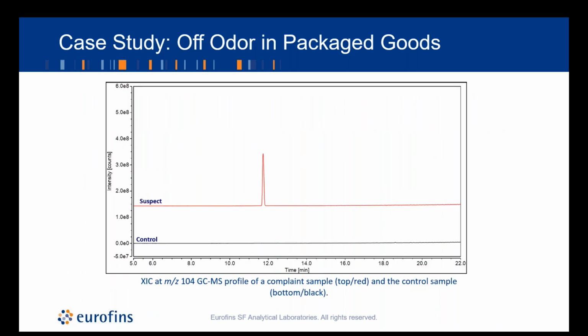So these are our sample chromatograms. Once again, in this case, these are a little different because up to this point, what we've looked at is total ion chromatograms, or TICs, which show the total ion intensity in our scan range throughout the analysis. What we're looking at here is extracted data, which is taken at one specific mass of interest. Extracting masses in this way can be very useful when you want to look for low levels of an analyte, and these extracted channels can also be used for quantitation if needed.